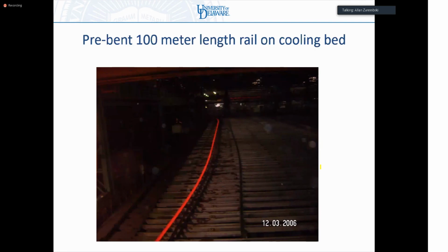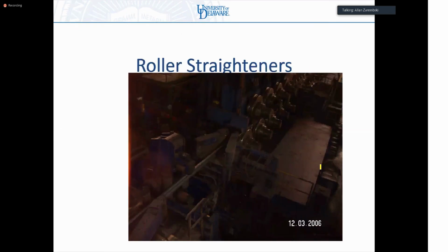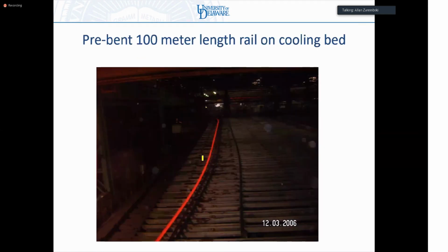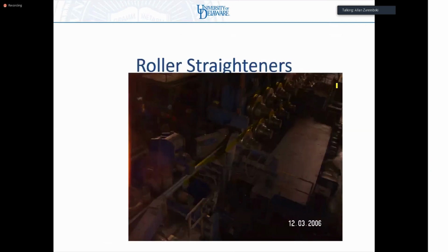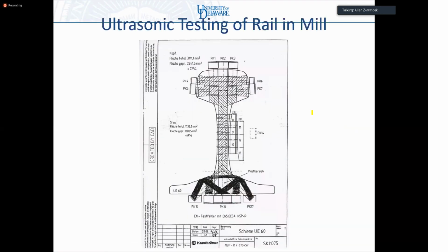There's the pre-bent rail on the cooling bed, exactly as they showed it in the movie. This is a roller straightener unit where the rail, which is right over here, is going through these rollers, which are straightening them out, because the cooling process introduces not only lateral distortion, it introduces vertical distortion. So there are both vertical and lateral roller straighteners to straighten the rail out. So you get the final straight rail you want at the end.